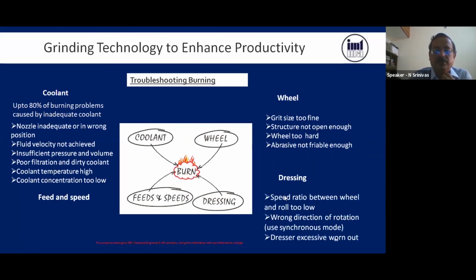Dressing speed ratio between wheel and roll, and wrong direction of rotation. Dresser excessively worn out. If a dresser is worn out, again instead of opening out the wheel, it will blunt it further. Then what happens? This will cause burning. So these are some of the tips for troubleshooting burning, and also feed and speed, more depth of cut. These are the influencing factors for burning.